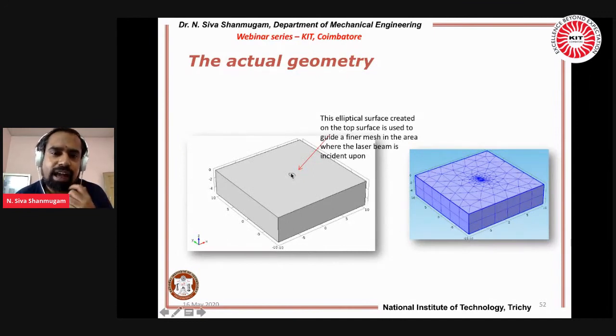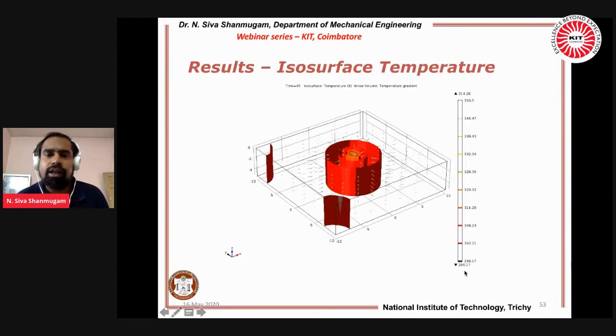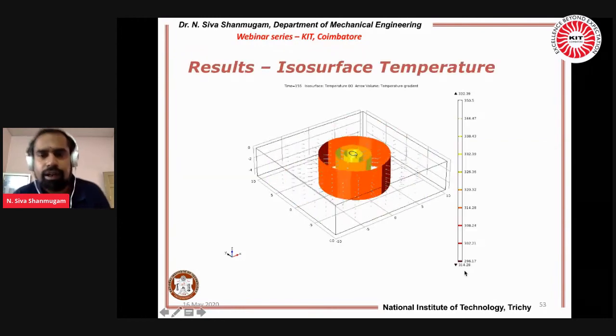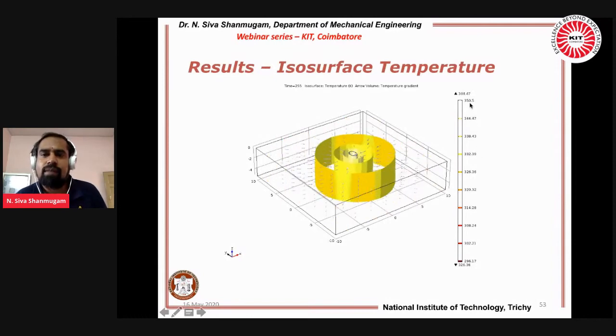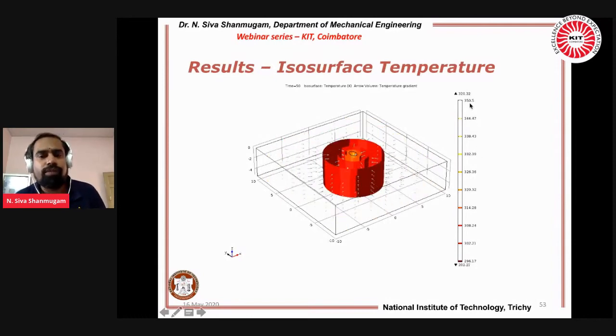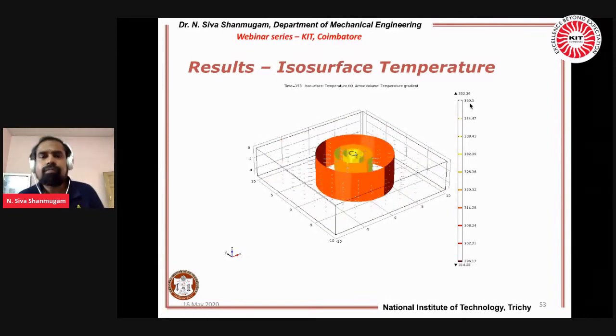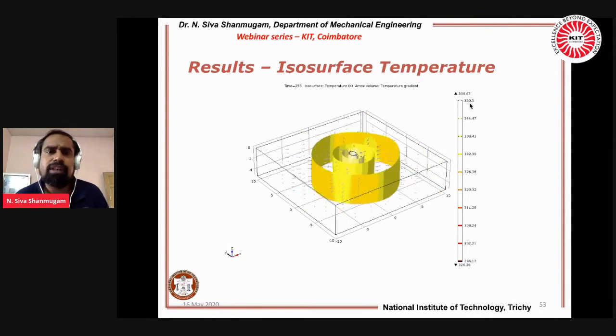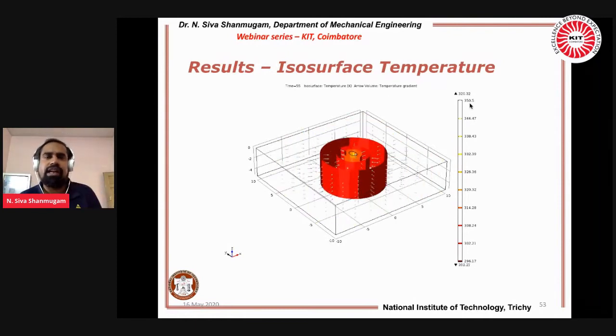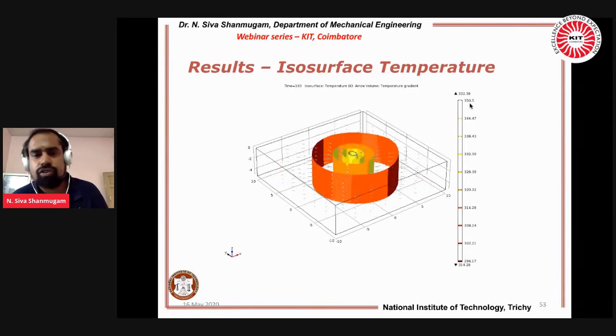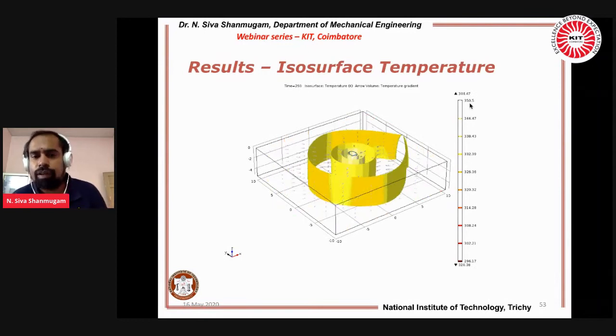This is the area where the heat source is going to, where the laser beam is going to impinge. This is the finite element model. This is the physical representation of the system. After meshing, you get the finite element model, and you can see the temperature distribution. Okay? This is only the glass slab. You are getting only something around 350 Kelvin. Depending upon the material, your temperature gradient will vary, and the peak temperature will also vary. It depends upon the melting point of the material.